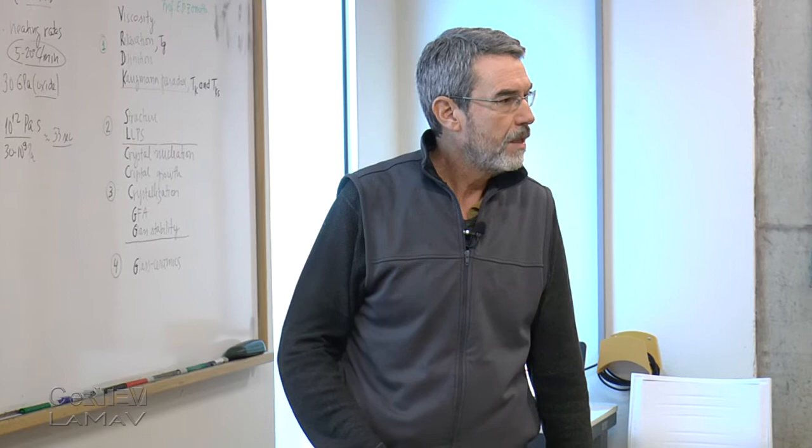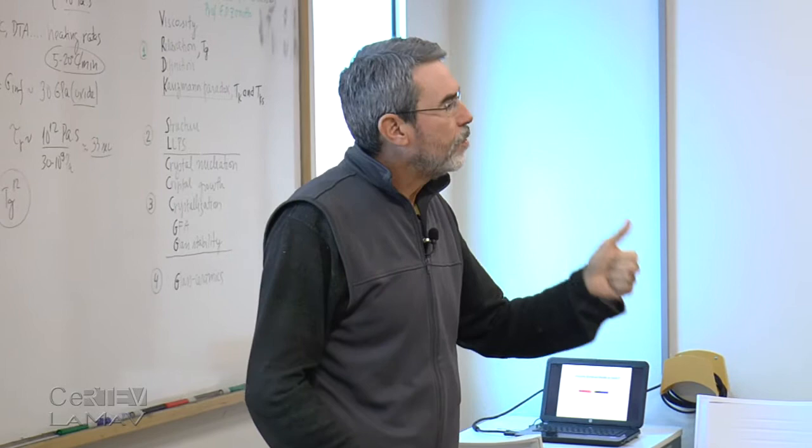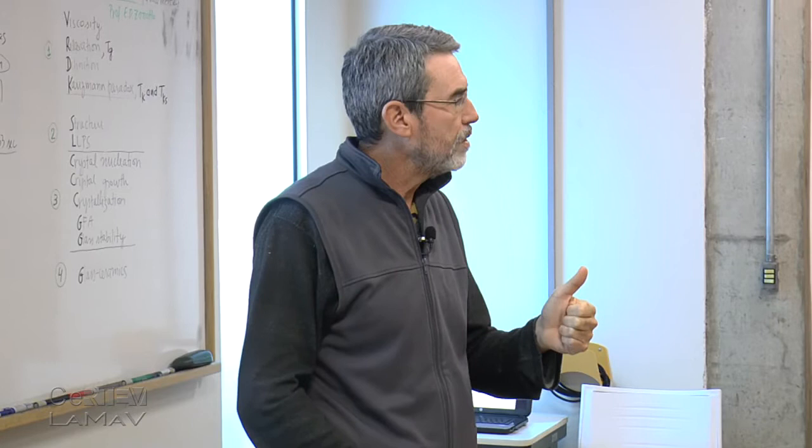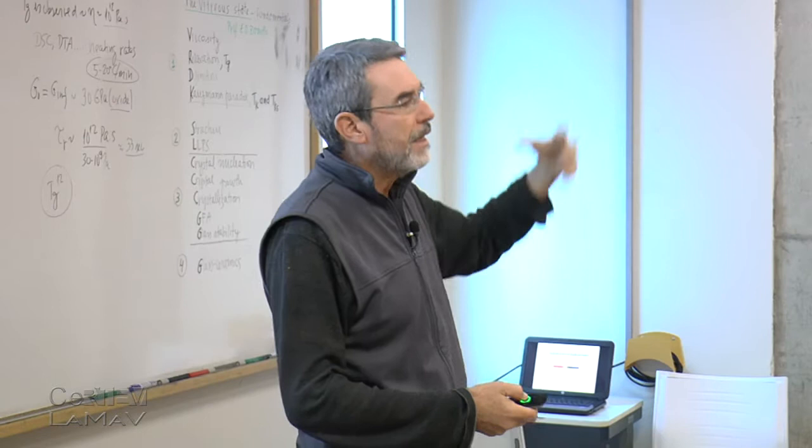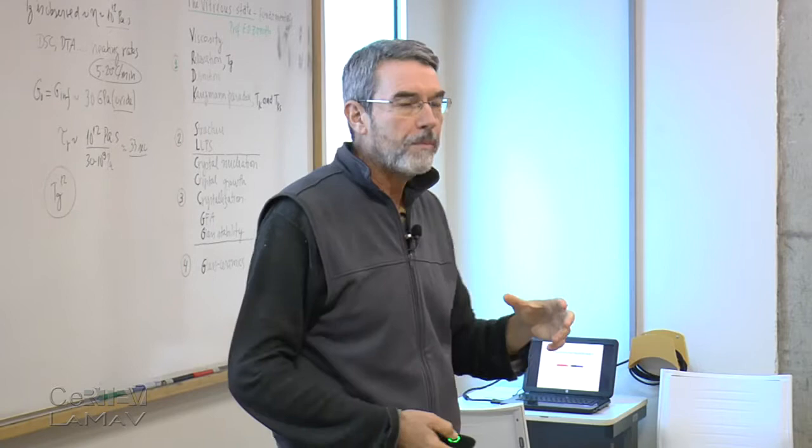So one key rule of thumb for a good glass forming ability: high viscosity at the liquidus. Materials which have a very high viscosity at the liquidus are good glass formers. In general, this is not the only parameter. There are thermodynamic parameters. Crystallization depends on kinetic and thermodynamic parameters, but that's a good one. If you had to choose one property for good glass forming ability, high viscosity at the liquidus.